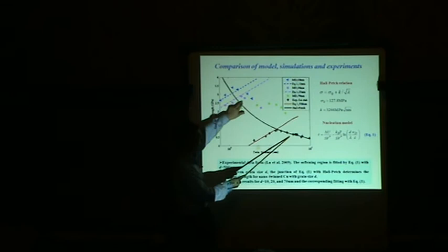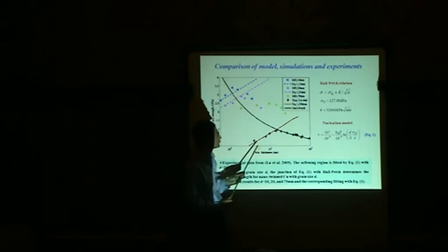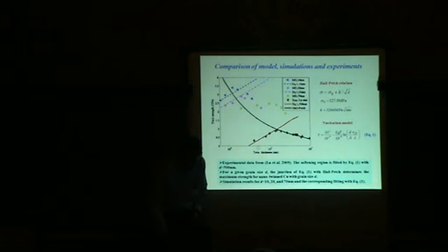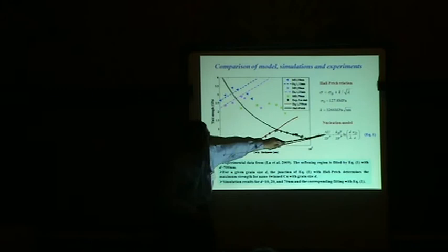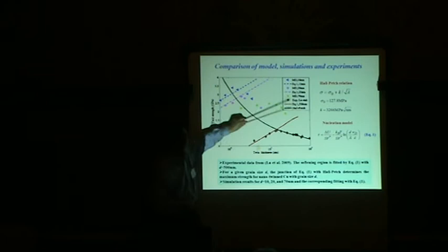Here's our new theory, the kinetic nucleation model, which captures this transition really well. But we have one fitting parameter here. The fitting parameter is activation energy. Because this activation energy is a fitting parameter, we can also vary it to fit our MD simulations. So by changing this one fitting parameter, we can fit experiments and also fit our MD simulation.